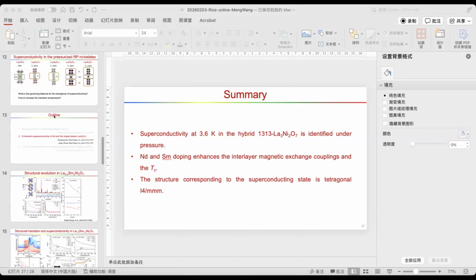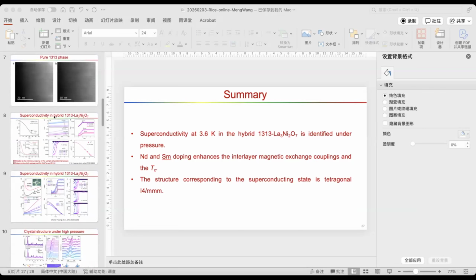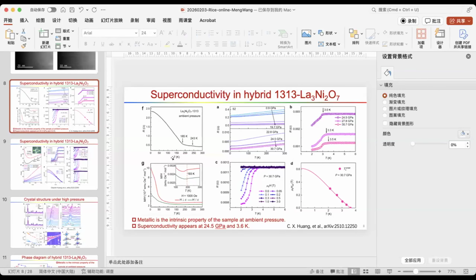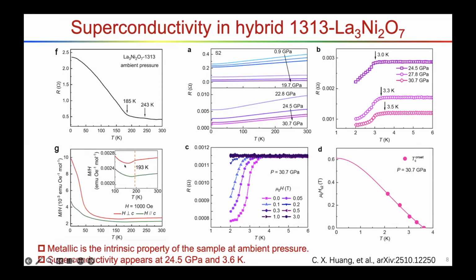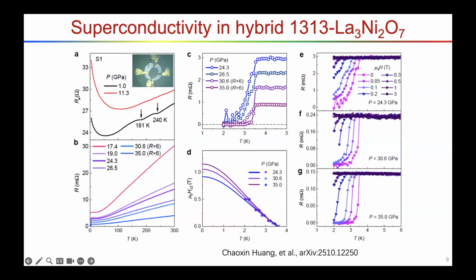Oh, I think so. Let me show you here. As you can see, it's actually more obvious in these measurements. There are two anomalies at different temperatures. I think they correspond to spin density wave transitions of the sample, but it's very complex. This is a 1313 phase. There is a single layer and trilayer. I think they may have different spin density wave transitions corresponding to different temperatures, but it needs more diffraction measurements.